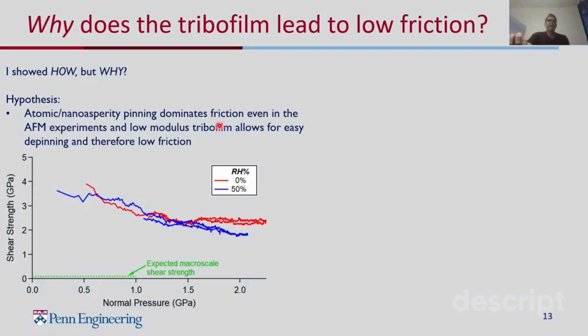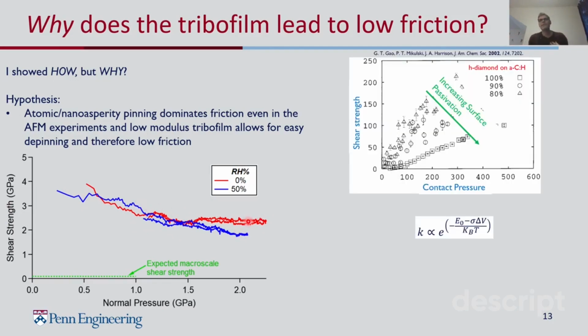And I'll show here again shear strength on the y-axis, and then the x-axis has actually been converted to normal pressure. Over this normal pressure range, the dependence of shear strength on normal pressure is approximately constant. If there's any change at all, it might be a negative slope here. And how does that compare to a case where we have interfacial bonding across the interface? We know what that looks like based on a number of simulation papers, and I give one example here.